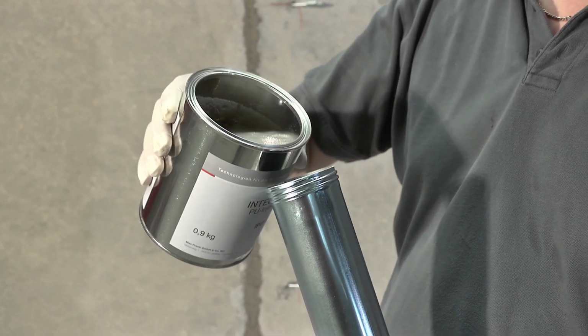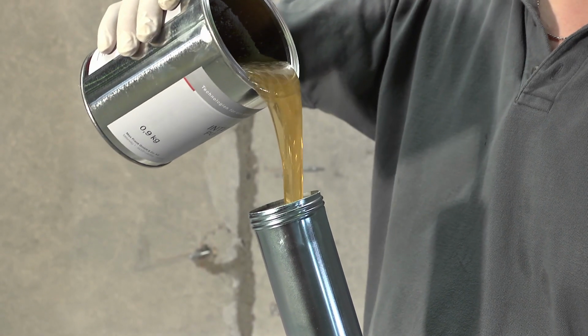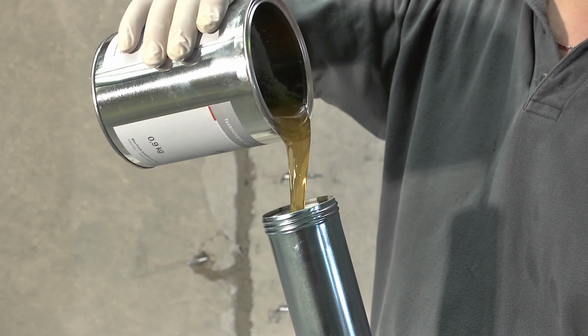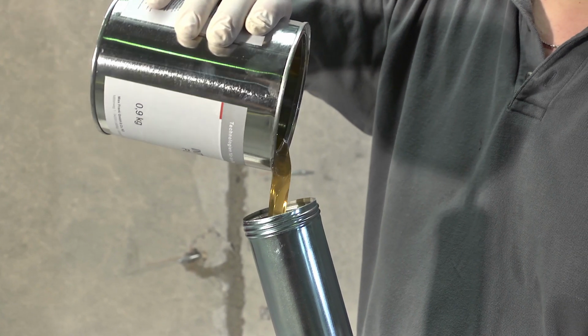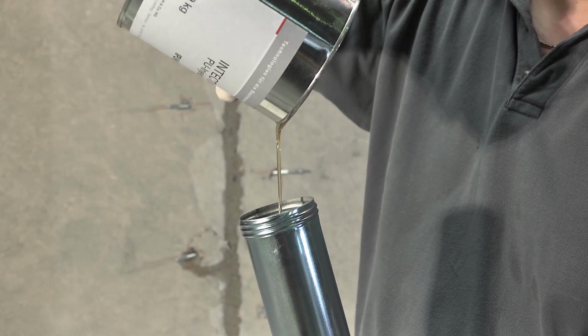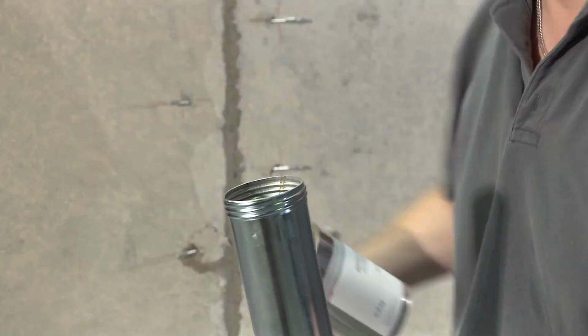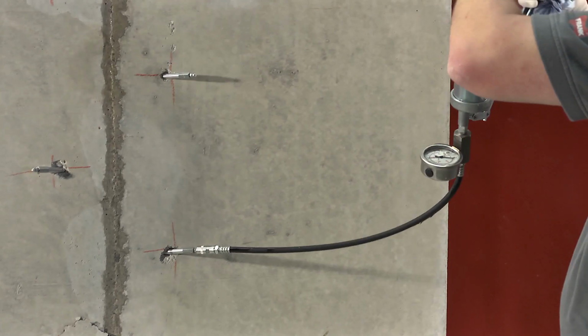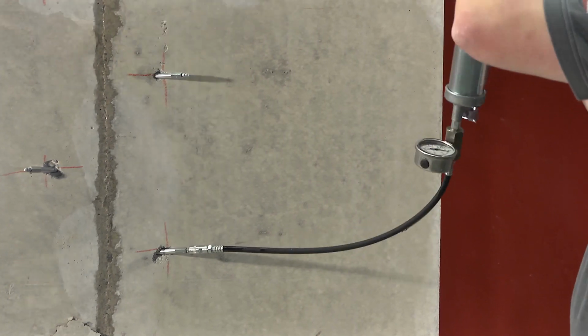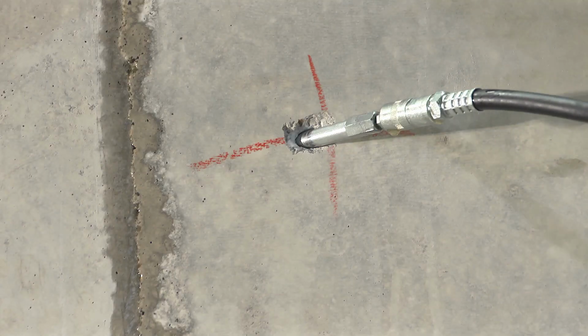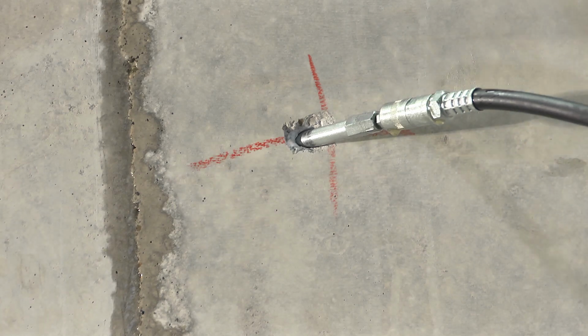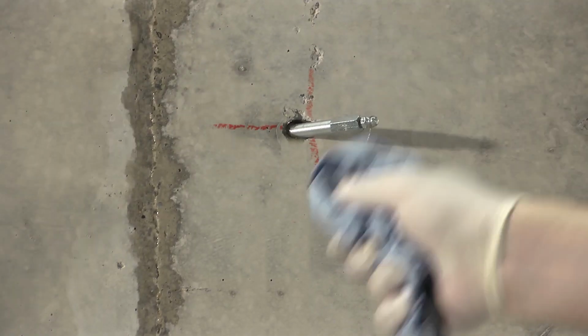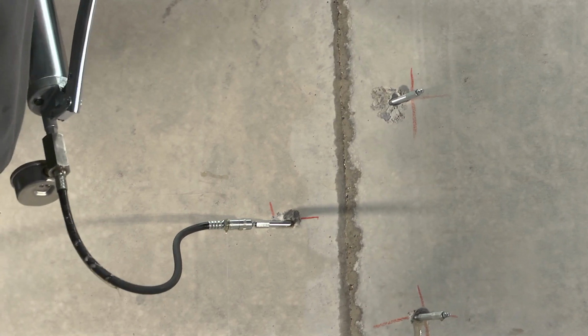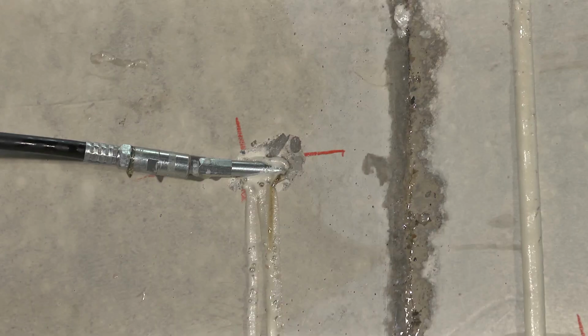The resin reacts on contact with the water. In so doing, it forms foam that stops the flow of water. Since the highly reactive Intectant Blitz may be activated by atmospheric humidity alone, always make sure to keep containers properly sealed. Inject Intectant Blitz into the leaking crack or joint using the already positioned packers. For vertical cracks, the ideal injection procedure is to start with the lowermost packer and work your way to the top in a step-by-step manner. For horizontal cracks, start on one side and work your way across to the other side.